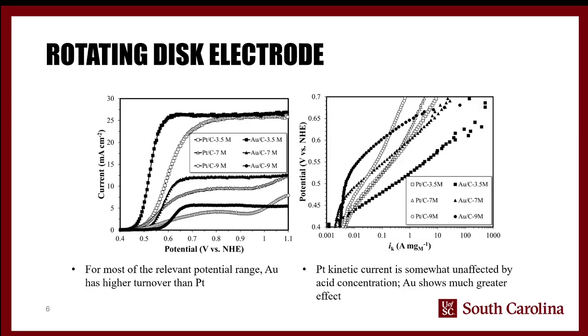So this is the summary of the results from the rotating disc electrode. There are two main takeaways here. The first is that acid concentration does make a difference. You can see that as we go from 3.5 molar to 7 molar to 9 molar, there's a pretty significant drop off in the limiting current that's achieved.